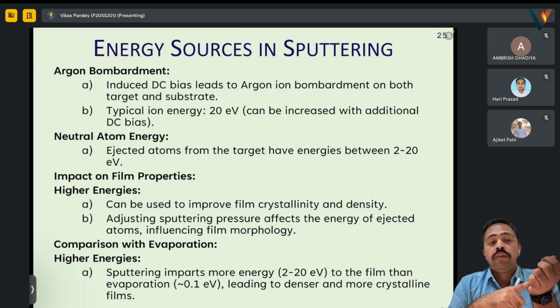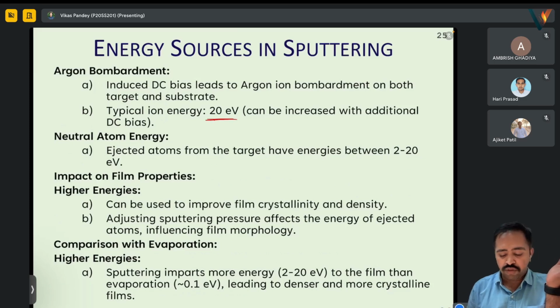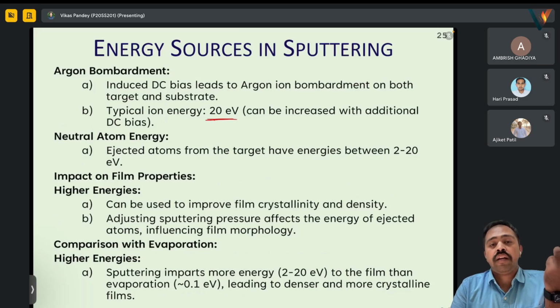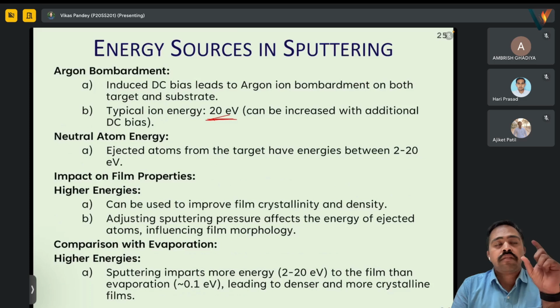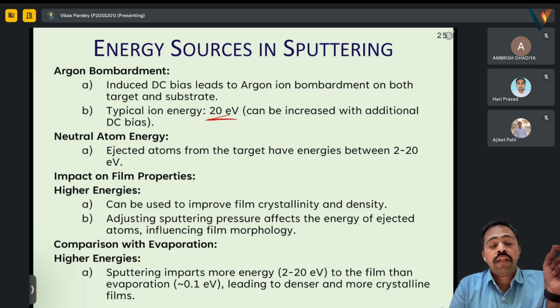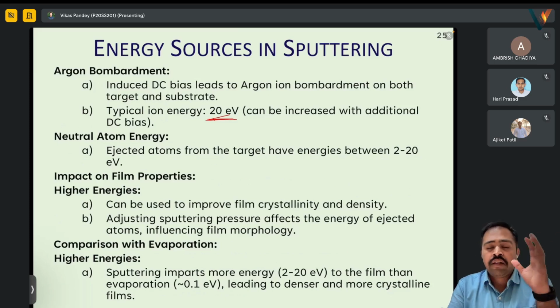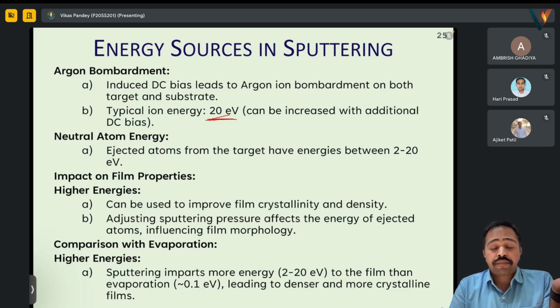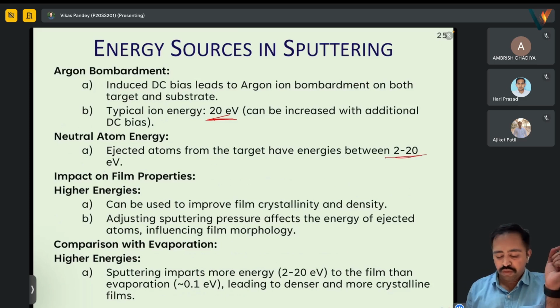This bombardment on both the target as well as the substrate is the energy source due to which the sputtering occurs. And this energy is typically in the range of 20 electron volt, and it can further be increased. If we are talking about RF, it can be increased by using DC along with RF, a combination of both. Then once this whole process is done, the atom is ejected from the target in the neutral form, and it still has energies between 2 to 20 electron volt.